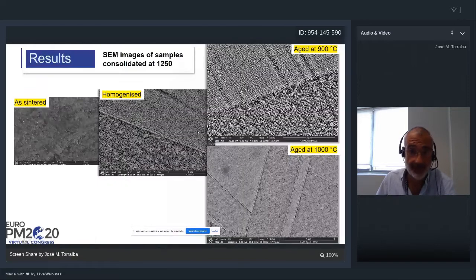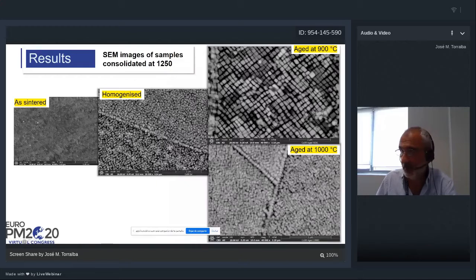Here we have the microstructure for the sample sintered at 1250 in the sintered state, homogenized and aged at two different temperatures. You can see that we perfectly develop the cuboid structure for the gamma prime precipitates. If we see it at higher magnification, it's more clear. You can see here how maybe this is the largest size of the cuboids, as we will see later with more